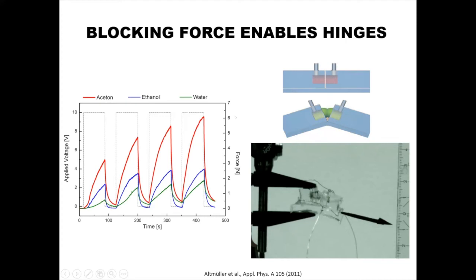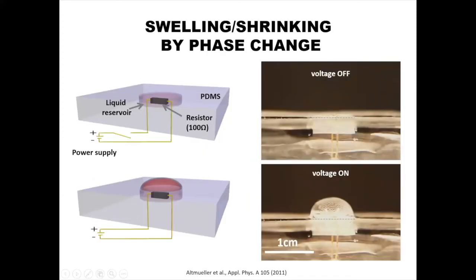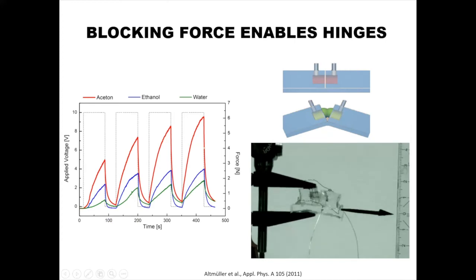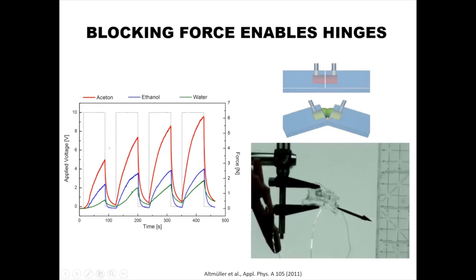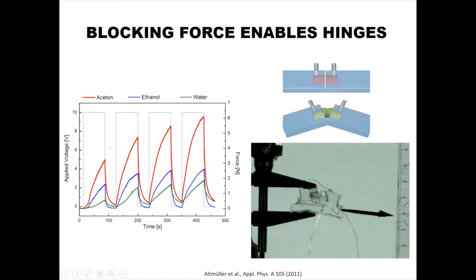And we can achieve forces up to 6 Newton, which for this little bubble, which is less than 1 centimeter in diameter, is quite a lot. The nice thing as well is when you see the expansion, it's quite fast. What was surprising to us is that when you need to cool down the liquid to go back from the gas phase, we assumed that would be a very slow process. But actually the elastomer membrane at the top is pushing back, and it has condensation.